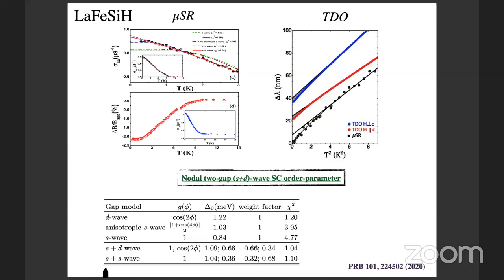and multi-gap isotropic models. We find that both the multi-gap models, nodal and isotropic, give the best fit, but the multi-gap nodal fit gives the minimum value of goodness of fit, so we conclude that there is a nodal two-gap superconducting gap symmetry in this sample.